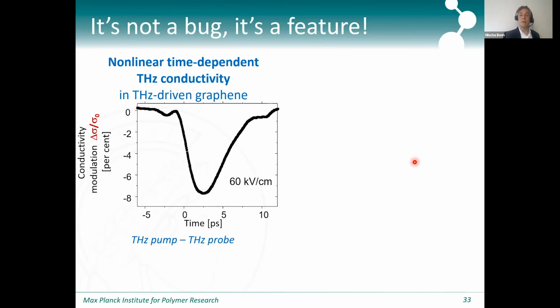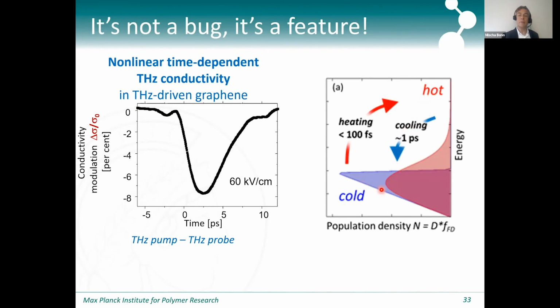What that means is that we start with a cold, room temperature Fermi-Dirac distribution of carriers in the system. We heat it within a few hundred femtoseconds, limited by the pulse duration of our terahertz pulse, which is 1 or 2 picoseconds. Then it takes a few picoseconds to cool again and to go back to this cold state. This is an important picture to have. We start off with a conducting material, we apply a moderate field for a very short time, it kills the conductivity, but the conductivity recovers on the time scale of a few picoseconds. All right.